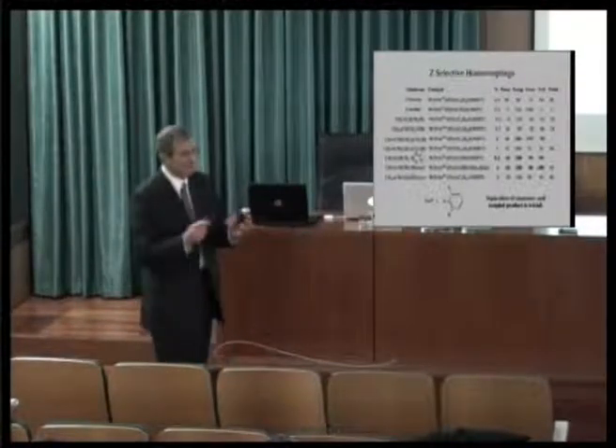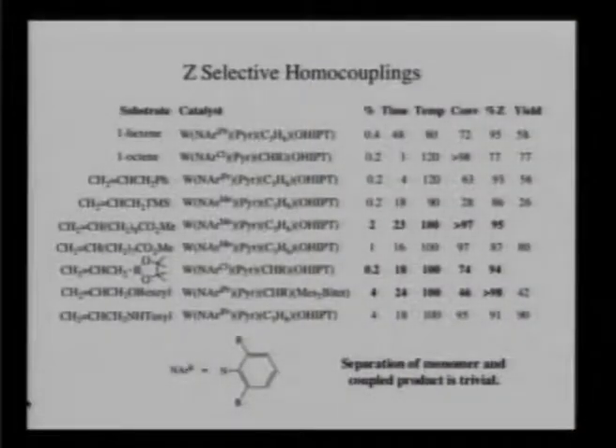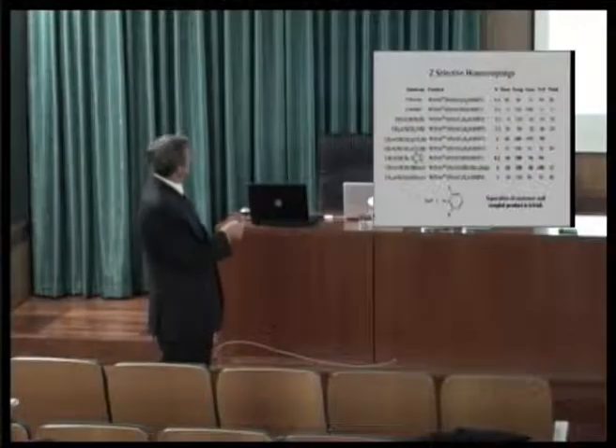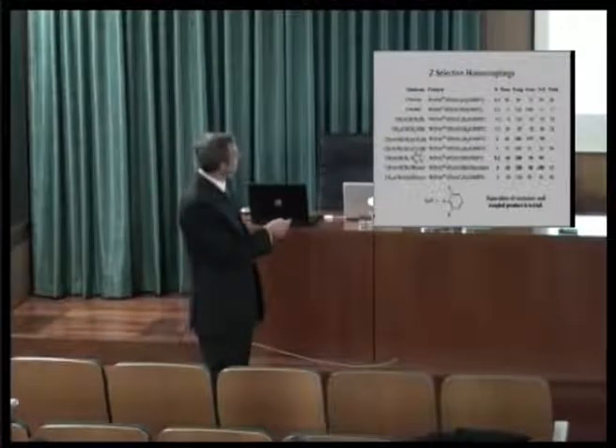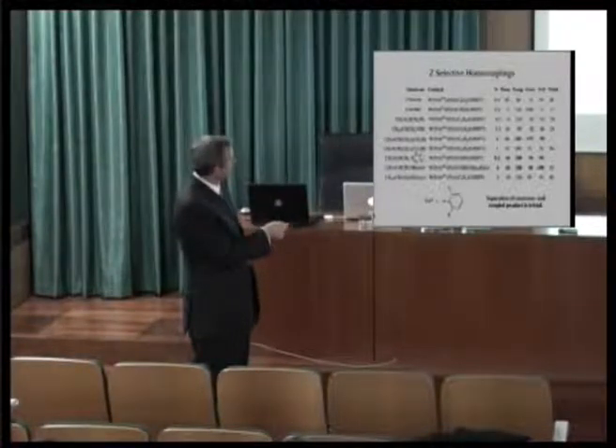So this too was reported in 2009. Here's a large table. I'll just point out a couple of things. One, the HIPT ligand, with one exception, is the only one that is successful. Two, tungsten is the only metal that is successful. And three, it doesn't appear that you need a small imido group. Any substituted imido group, diisopropyl, dichloro, or dimethyl, is successful for tungsten. It takes time. It doesn't go at room temperature, so you have to heat up between 80 to 120 degrees, I think, in one case. The loading is anywhere from a typical 1 or 2% down to as low as 0.1%, I believe now.